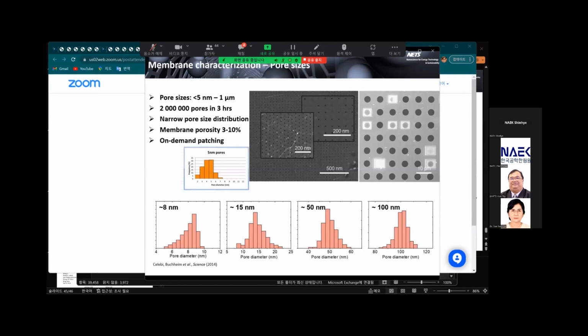You might worry about the long process time of perforation, but we could drill a few million pores within a few hours. Although focused ion beam cannot warrant scaling up of the graphene perforation process, one of the clear advantages of this method is that one can end up perforating a wide variety of pore sizes. Indeed, we could drill on graphene pore sizes of 5 nanometers, 8 nanometers, 15 nanometers, 50 nanometers, 100 nanometers, etc., all the way up to 1 micrometer.